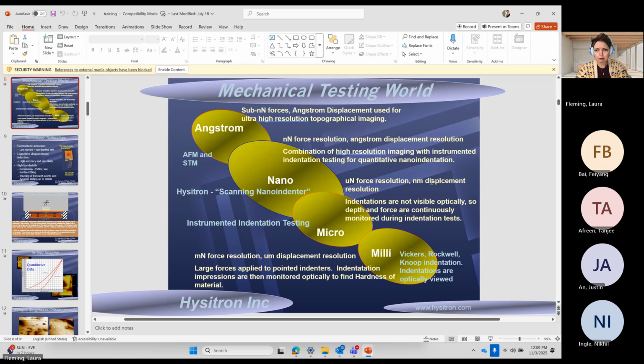We are continuously monitoring both the force and displacement during that test. That allows us to measure that hardness and modulus. On the other end of the spectrum is AFMs, where you're running a sharp probe across a sample surface where you have sub-nanonewton forces, you have angstrom displacement, and you can get very high-resolution topographical imaging. Now, these are not indents. This is just a scan of the sample surface. There are some AFMs with tapping modes where you can interact with the sample and get some other information.